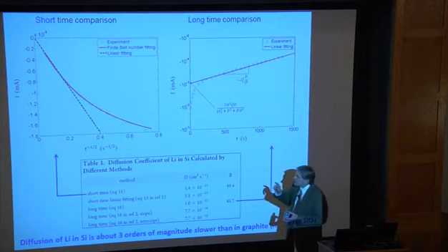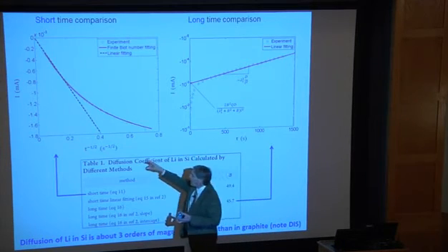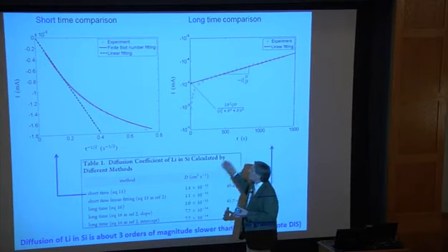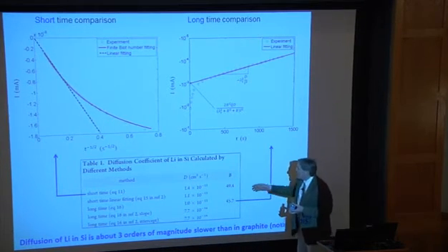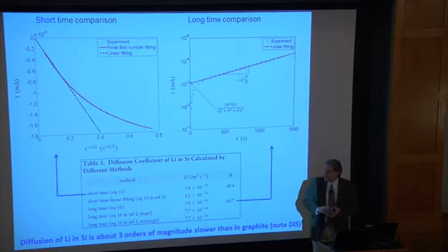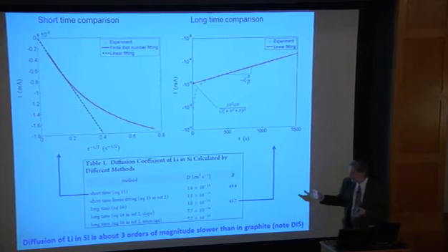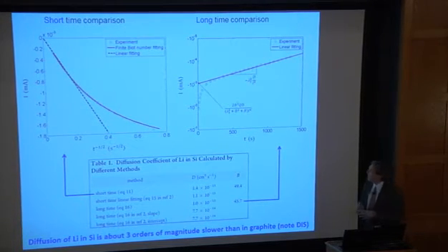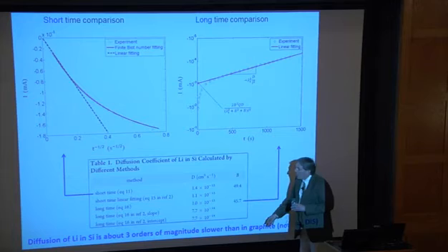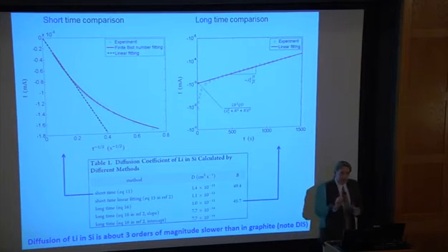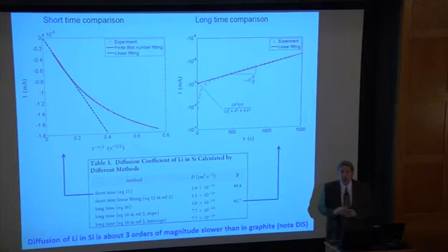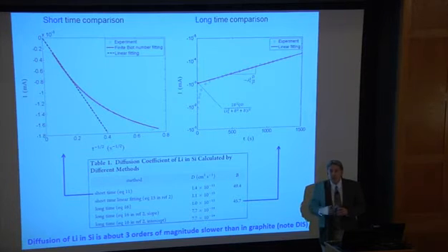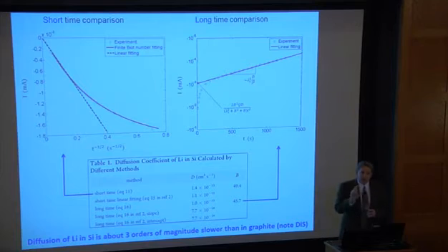So here we see on the left the current versus 1 over square root time, and for the short time solution. The long time solution, we had basically the same values for the Biot number that we fit to it, this ratio of resistances, diffusion to interfacial kinetic resistance. One of the key points that you can get out of this type of analysis, because now you're measuring a property of the material, is that diffusion of lithium in these silicons that are of interest for electrode materials is about 3 orders of magnitude slower than that in graphite. So it's going to be a challenge to get the power out of these systems. That leads to a whole other way you might architect batteries in order to make them viable for electric vehicle applications.